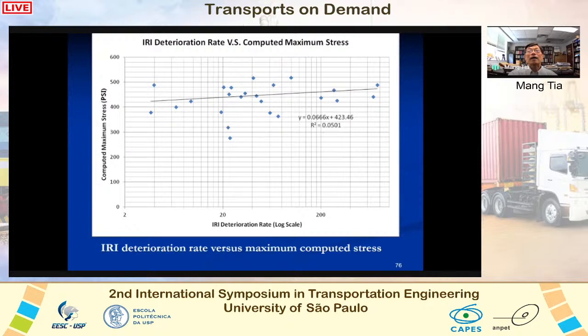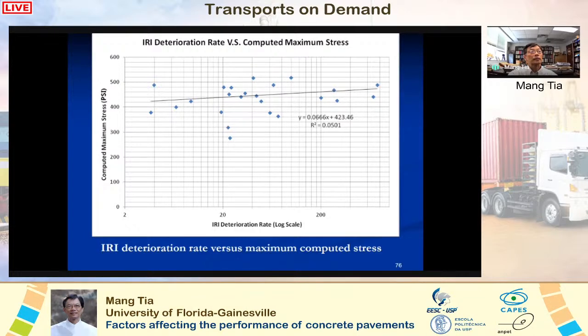So a higher IRI deterioration rate represents worse performance. This is a plot of the computed maximum stress versus IRI deterioration rate. A higher computed maximum stress is related to a higher IRI deterioration rate. However, the correlation is not very good, as seen from this low R square value.